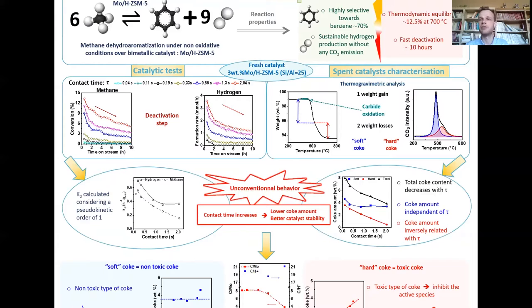From this data, it is possible to plot the deactivation constant calculated assuming a pseudo-kinetic order of 1 for each contact time. On the right, we can see the spent catalyst characterizations recovered after 10 hours of reaction.